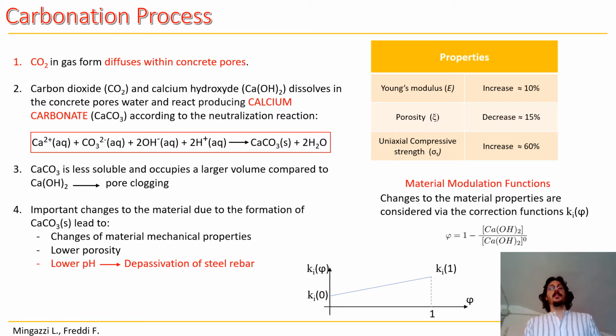Therefore, this translates into a lower porosity of the concrete and a change in the mechanical properties of the concrete as well. Moreover, the value of the pH is lowered, and once the carbonation front reaches the steel rebars, the depassivation of the steel rebars takes place as well. In order to account for the changes in the material properties, we introduce the material modulation functions, which are functions of the ratio between the current concentration of calcium hydroxide and the initial concentration.